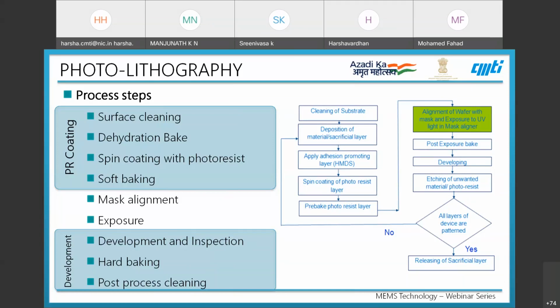Above which a spin coating of photoresist layer is done. After the photoresist is coated, there is a pre-bake of the photoresist layer, and then we move ahead with alignment of the wafer with the mask and exposure to UV light in the mask aligner.